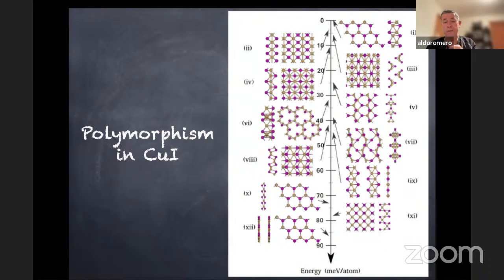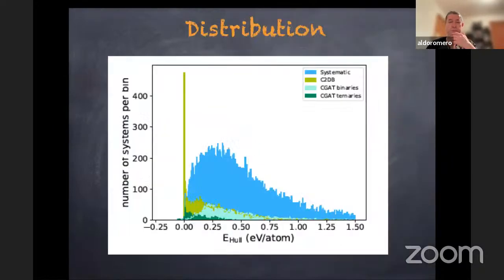The other thing that we keep in mind is, for example, that we can see polymorphs. That means that in the binary, in this particular case copper iodine, by a small difference in energies we can see a very large number of different crystal structures in 2 dimensions. If you go from 0 up to 10 milli-electron volts per atom, 20 milli-electron volts, you see that the number of structures changes, the coordination changes, the shapes change, and so on. Therefore, this represents the fact that you can have many different crystal structures using the same chemical composition. And this is how we obtain the distribution of the different crystal structures.